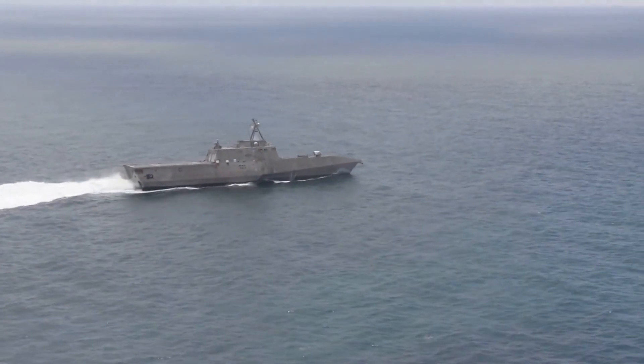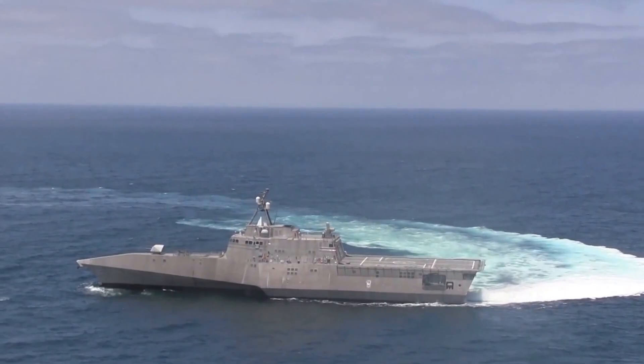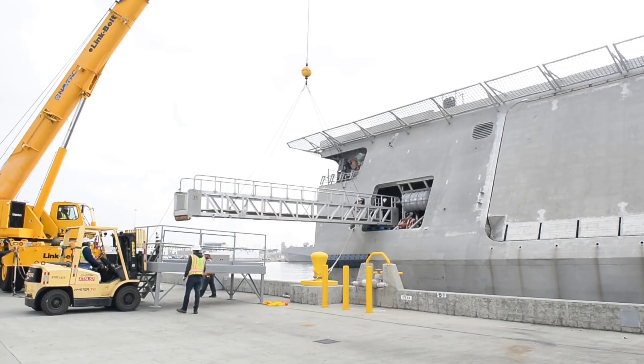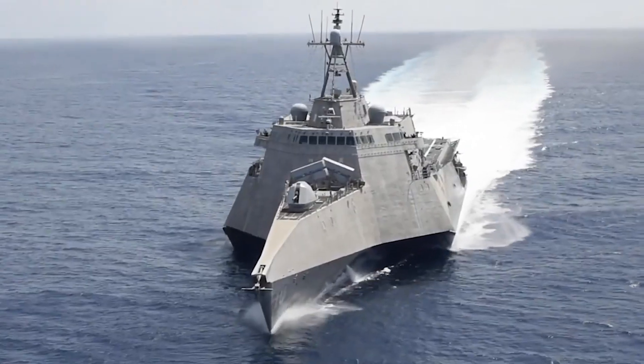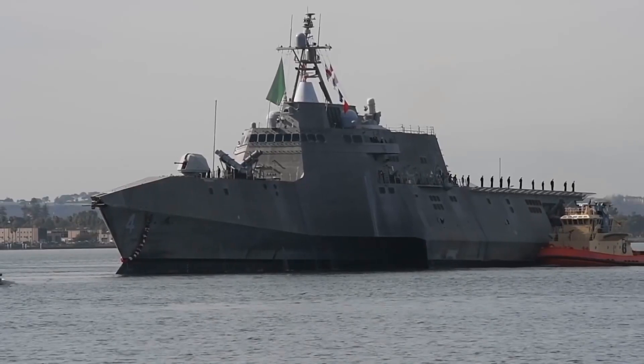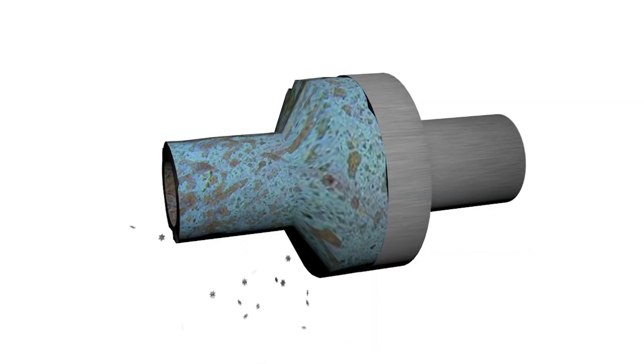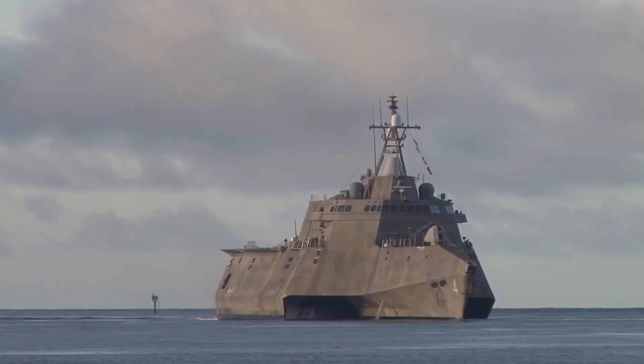However, these Navy warships have a number of serious problems. For instance, in 2010 the Navy discovered aggressive corrosion around the Independence's engines. The problem was so bad that the barely-year-old Independence LCS had to be laid up in a San Diego dry dock so workers could replace whole chunks of her hull. In contrast to the first LCS, the steel-hulled USS Freedom, Independence is made mostly of aluminum, and that's one root of the ship's ailment. Corrosion is a $23 billion-a-year problem in the U.S. military. The 418-foot-long warship was dissolving due to a major design flaw. Austal USA, Independence's Alabama-based builder, calls it galvanic corrosion — what occurs when two dissimilar metals in electrical contact with one another corrode at different rates.